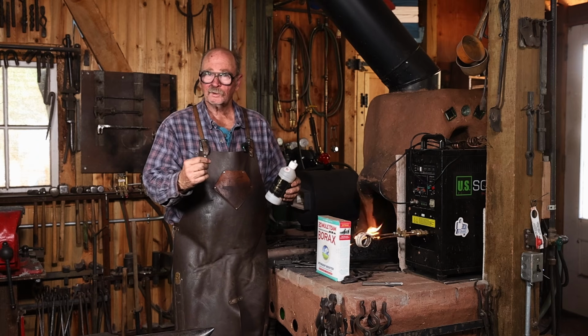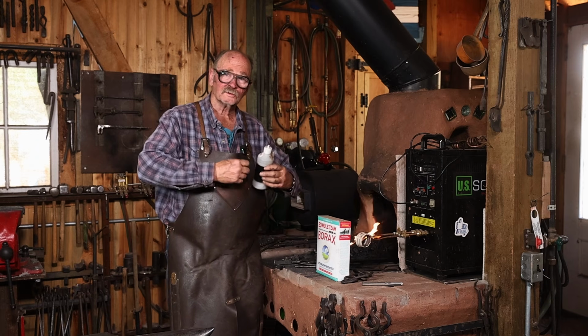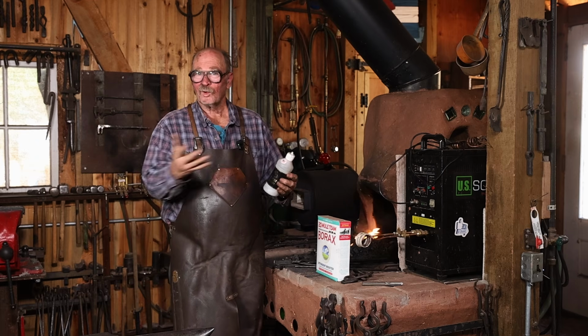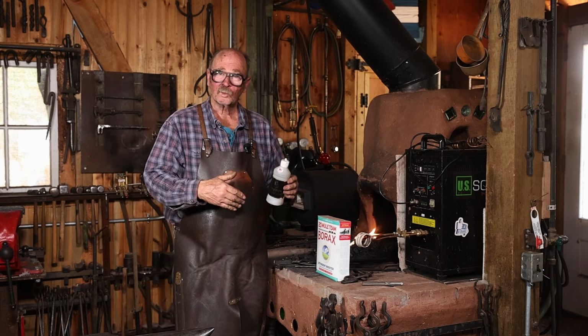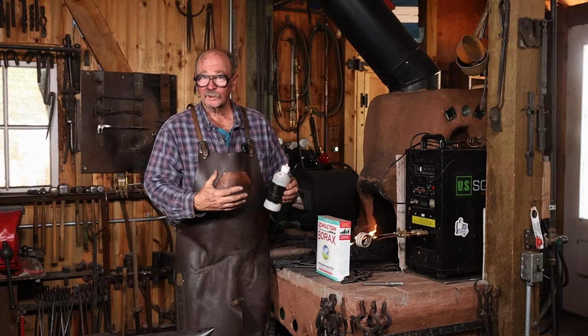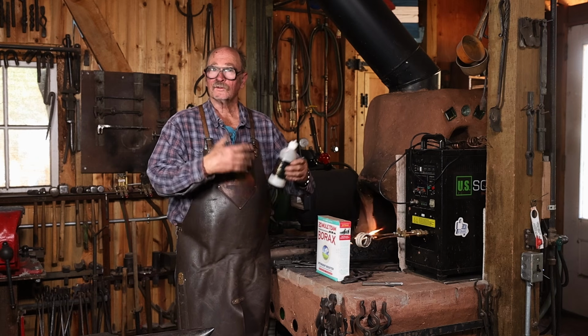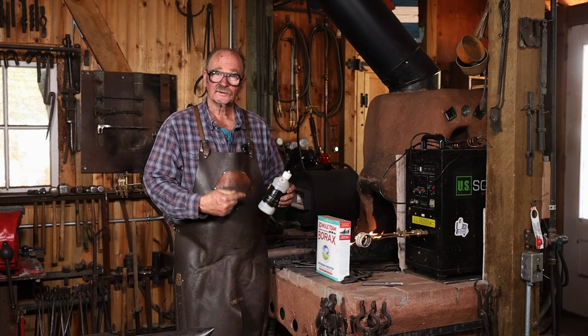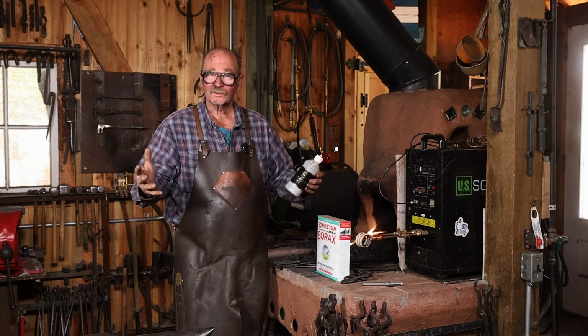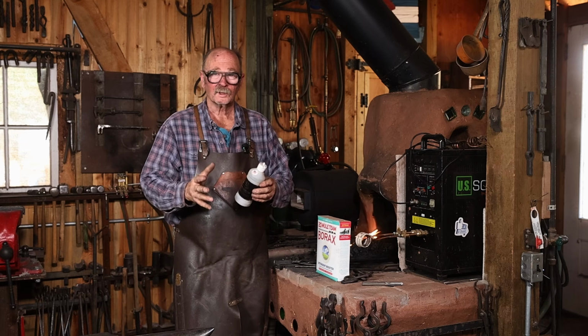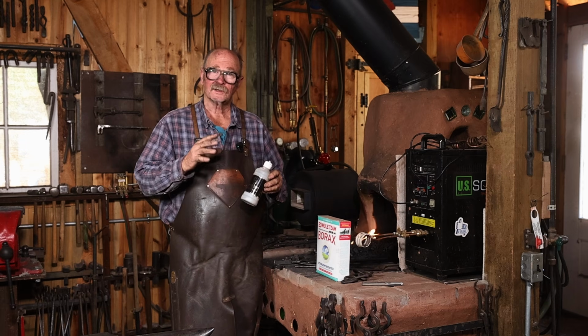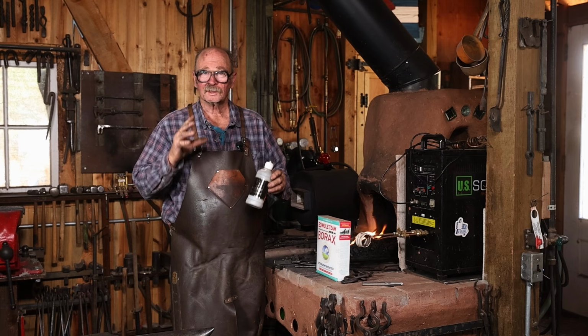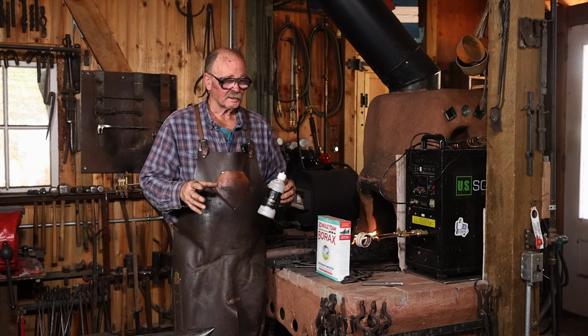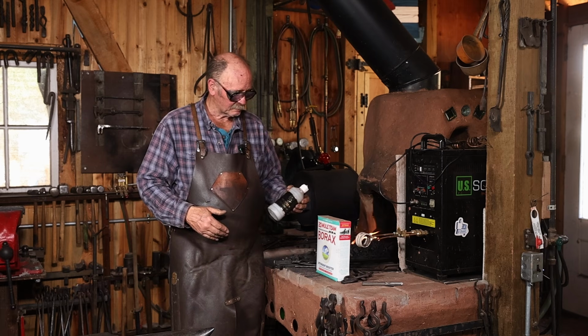And those first few hammer blows of a forge weld where you see all those sparks, well, that's the molten flux flying off. So if your weld is designed properly and you set the weld properly, all the flux and all the crud that's been caught up in the flux gets squeezed out of the weld so there's nothing trapped in the weld. But it isn't magic. If you've got a dirty fire, if your fire is not deep enough, if it's an oxidizing fire, flux is probably not going to make the difference.